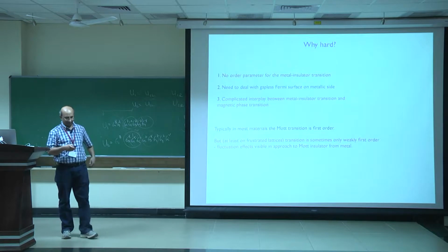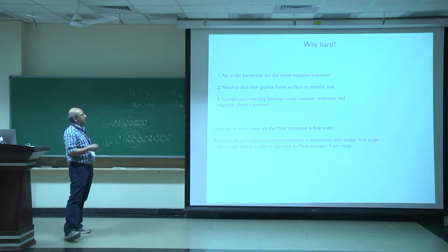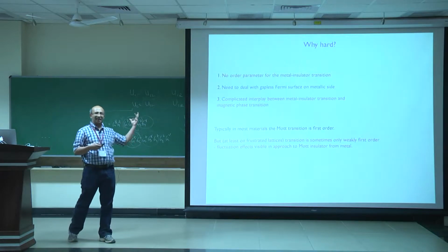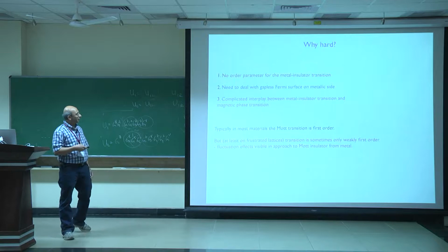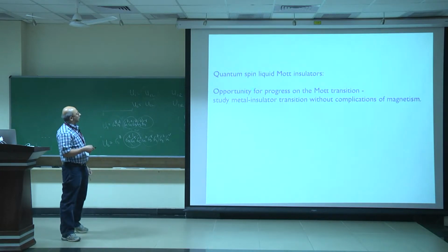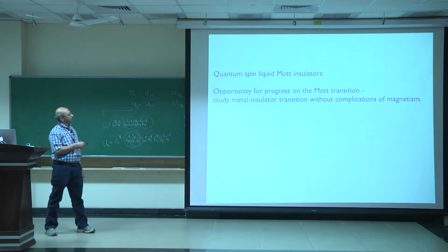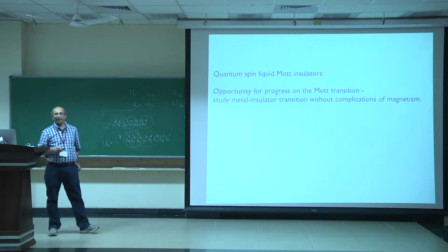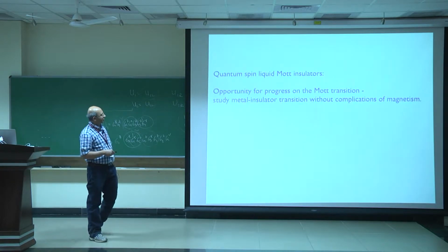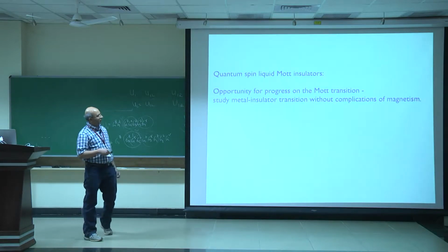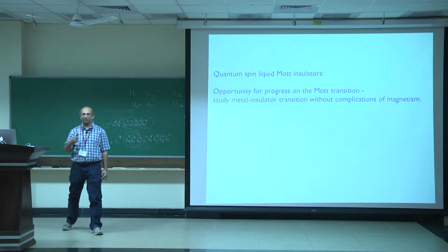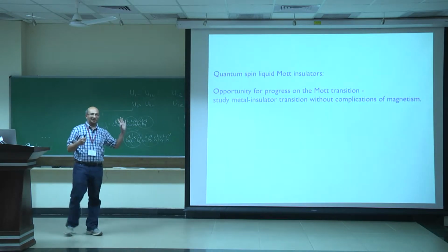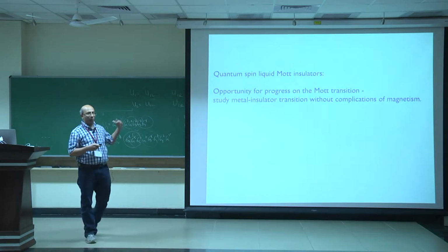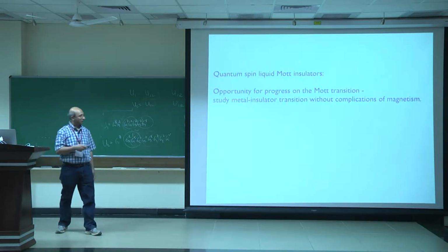So how do you deal with these kinds of things? We don't know, and that's why the problem has remained open and central to a large number of phenomena in the field. So what I'm going to talk about today, as I described in my previous lectures, is that we now know there's a class of Mott insulator that does not have any magnetic long-range order, namely these quantum spin liquid Mott insulators. So these provide us with an opportunity to make progress on the Mott transition, on the phenomenon of the metal insulator transition, without the complications of magnetic long-range order, right? So at least one of the things that complicate the study of the Mott transition, we might have hoped is gone for this class of phase transition.